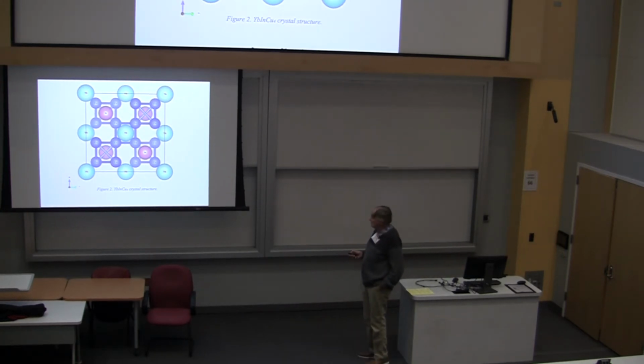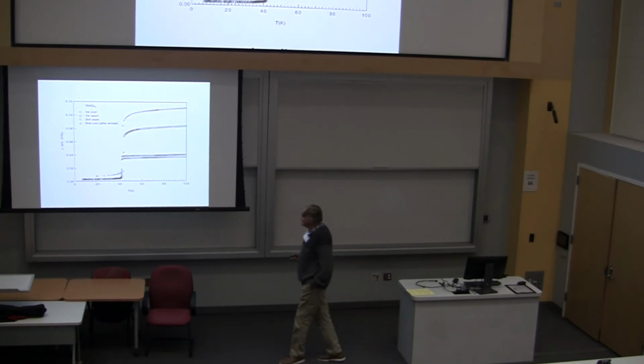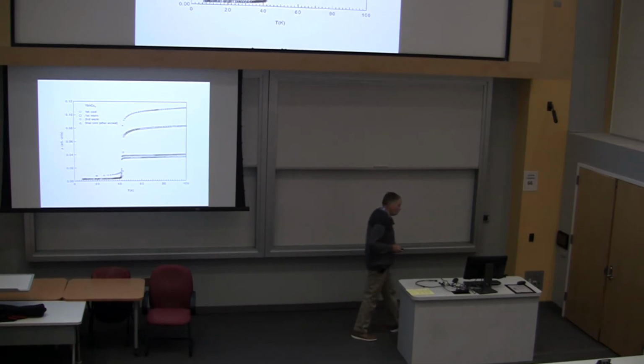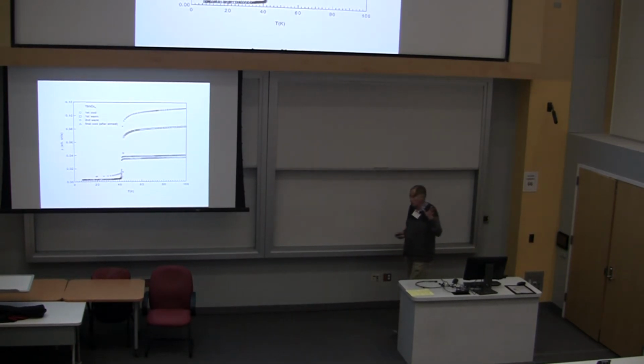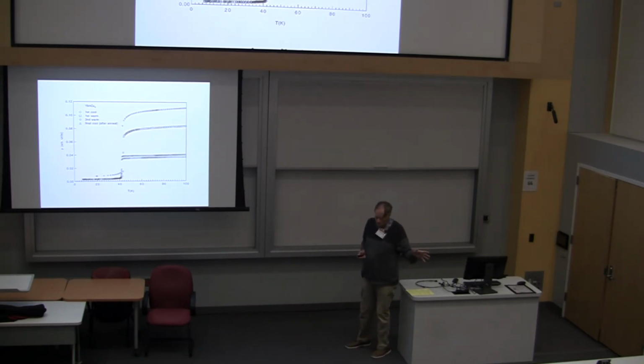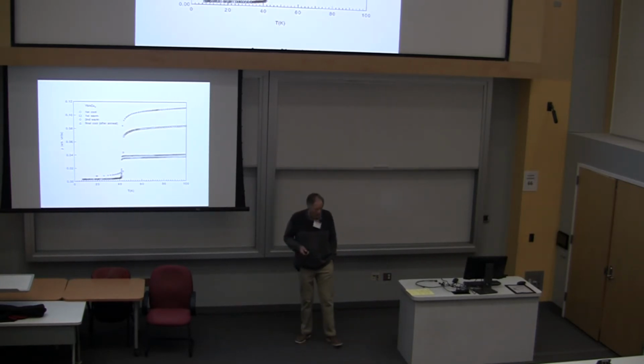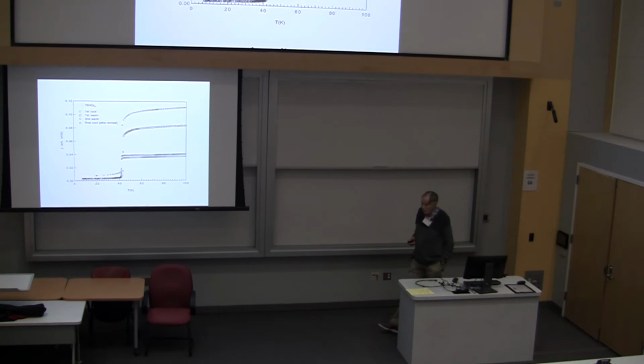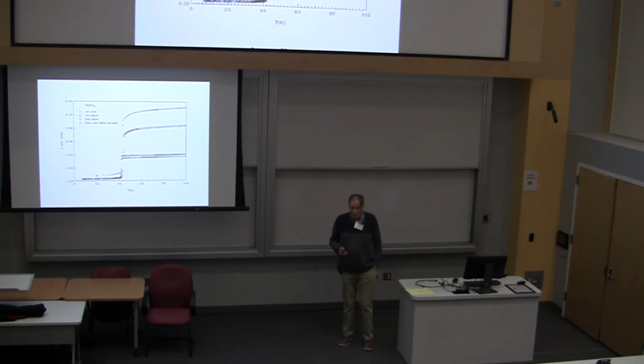And so we tried growing single crystals, and so I made an indium copper flux and put ytterbium in it, and instead of having a 10 or 20 degree spread in the transition width, we got these crystals that had a transition width of 1 or 2 degrees. And it turned out that the indium copper ratio in there was not 1 to 4 or whatever. It turned out that I was careless, and the ratio that I used was 1 to 1, and this is what came out.